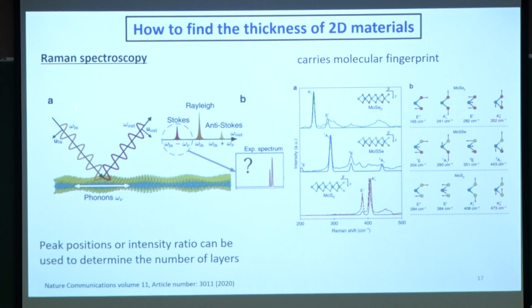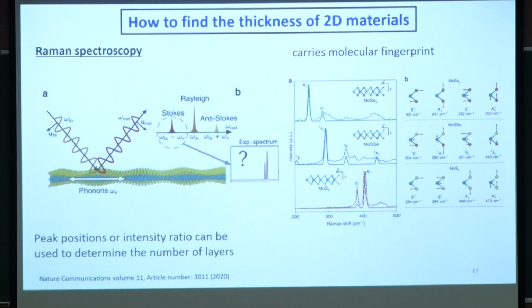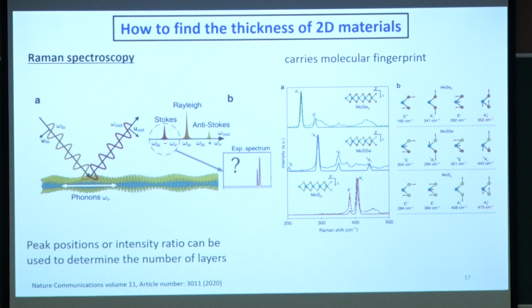So again, Raman spectroscopy uses two different things to identify the thickness of the two-dimensional material. One is the peak position or the intensity ratio. If it is TMDs, like MoS2 or something, then what you need is the peak position, the spacing of the peak, to identify whether it is monolayer or bilayer, or it may be bulk.